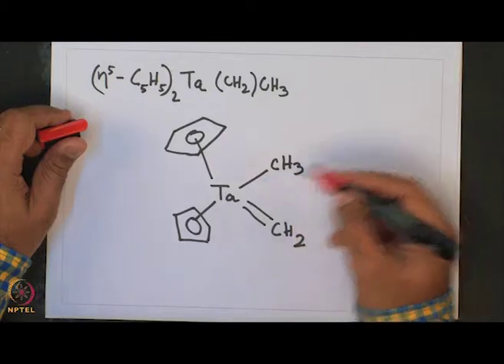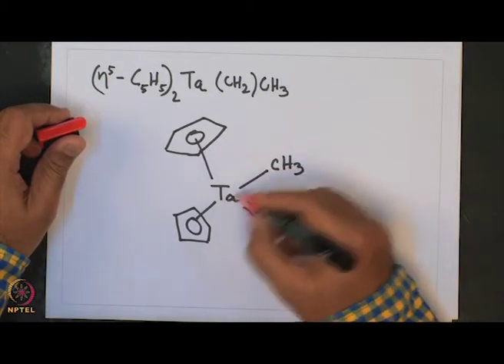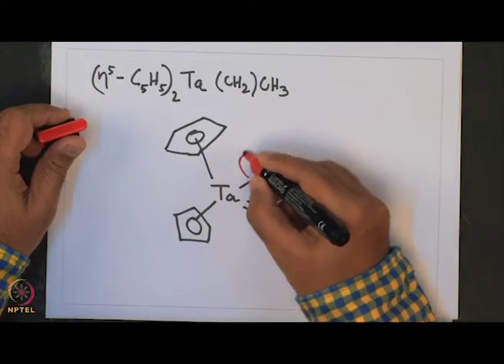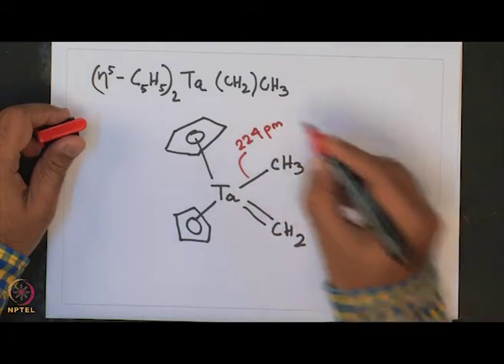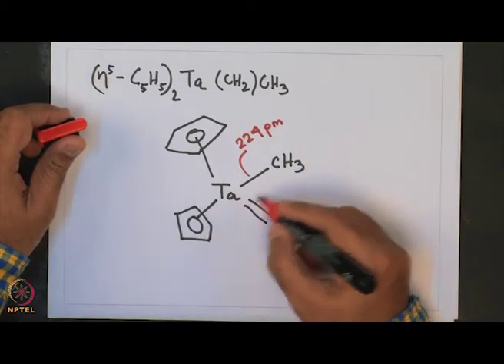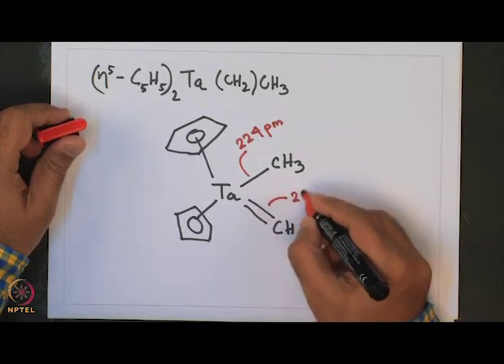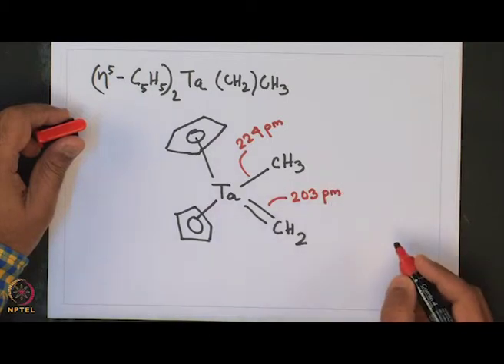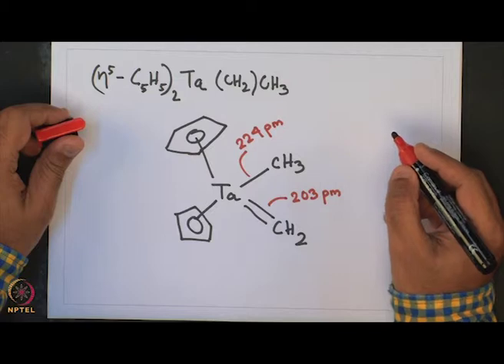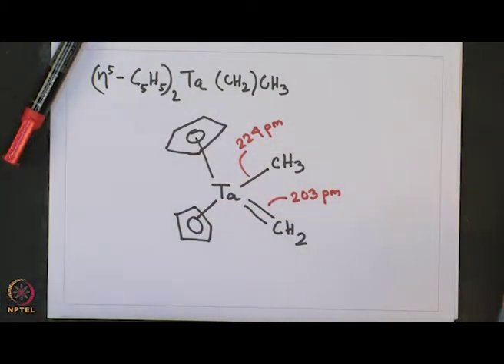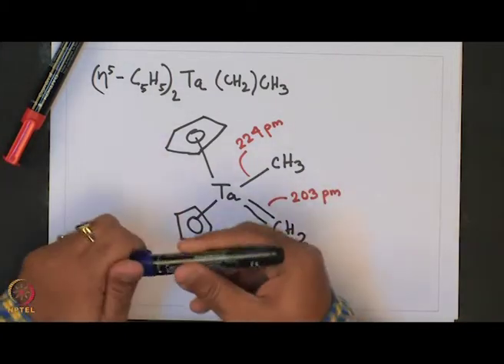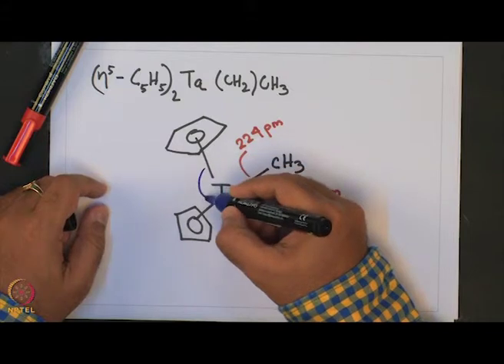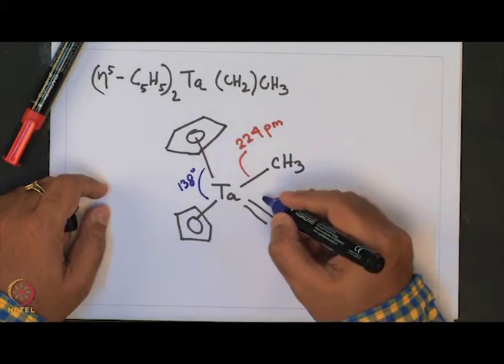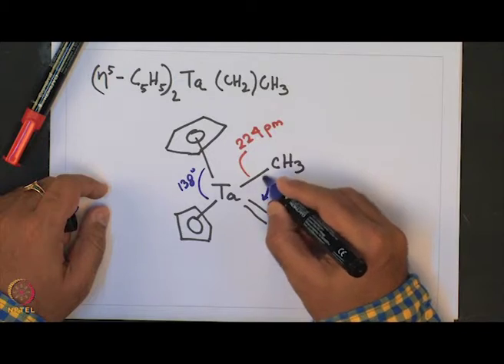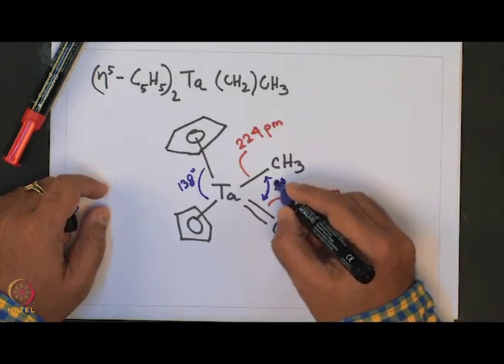and that is obvious from the bond distances. This tantalum methyl bond is much longer at 224 picometer, whereas because of its multiple bonding nature this tantalum carbene bond is way shorter at 203 picometer, and the angle between the two Cp and the tantalum is 138 degrees, whereas between the two tantalum carbon bonds this is about 95 degrees.